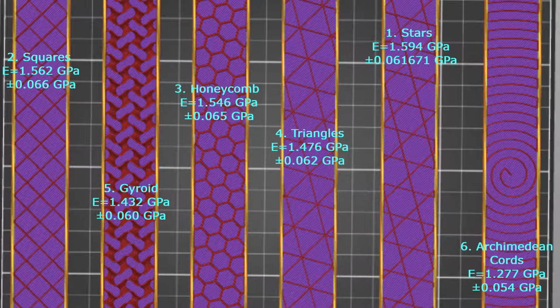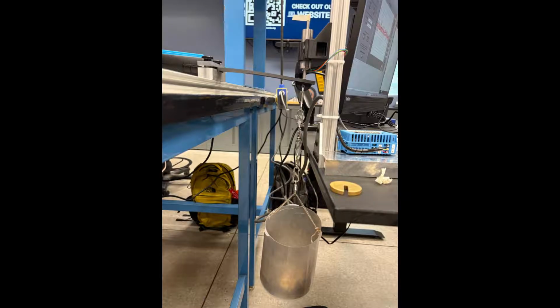The other patterns, all of their Young's modulus values fall in between this range. Once the mass of the beam is divided out, the efficiency of each pattern from greatest to least is in the same order. Note that the Young's modulus values are not exact for each pattern. These calculated values are strictly relative to this experiment, as they allowed us to determine which infill pattern is stronger relative to one another. This claim is validated by further testing with different sized beams, aka the 9mm beams.